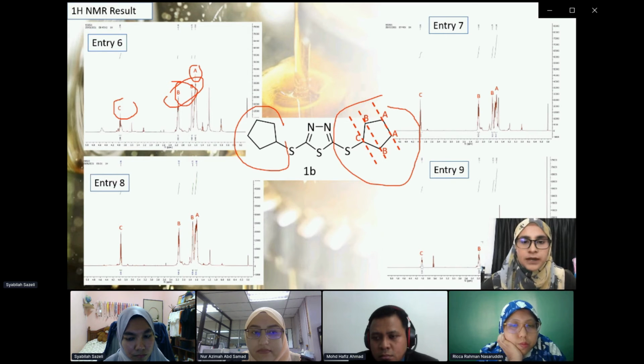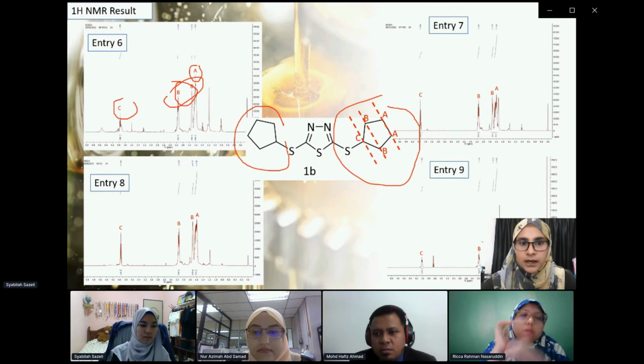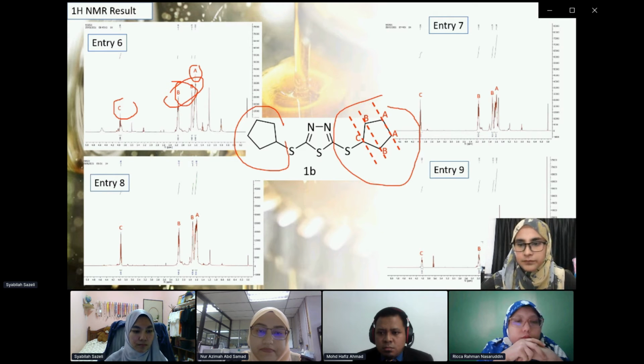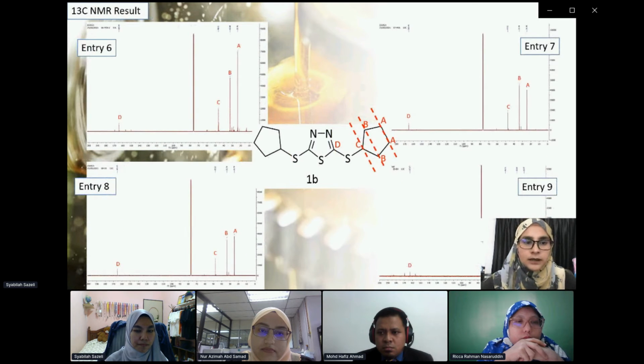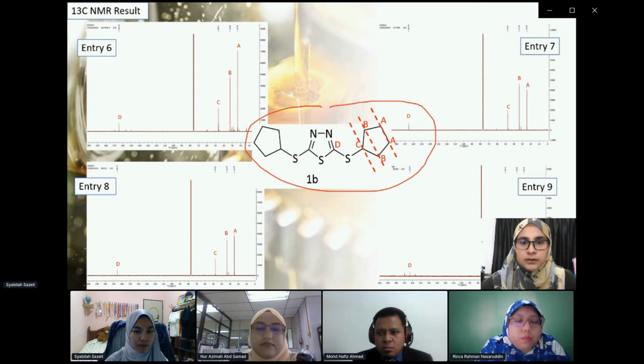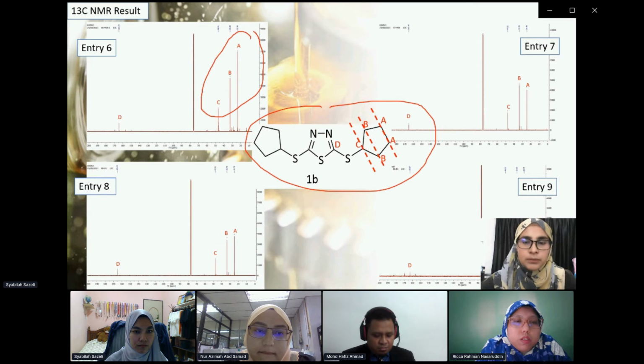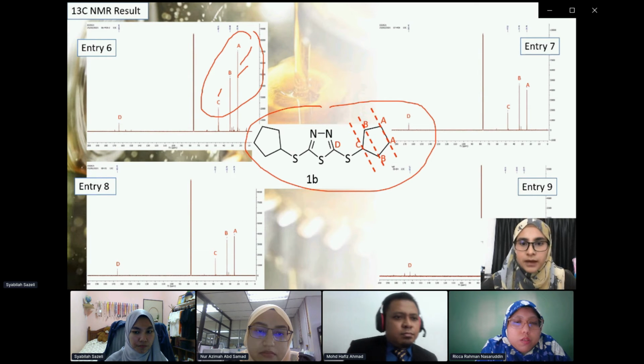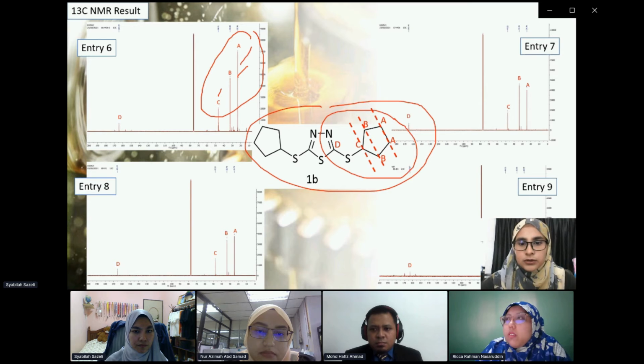So, the carbon NMR plays a main role to prove which compounds are isolated after column chromatography. For carbon NMR, the result fits the structure of this alkylated thiadiazole compound. We can see that the aliphatic side shows 3 peaks of A, B, and C, which is the total number of carbons contained in the cyclopentane.